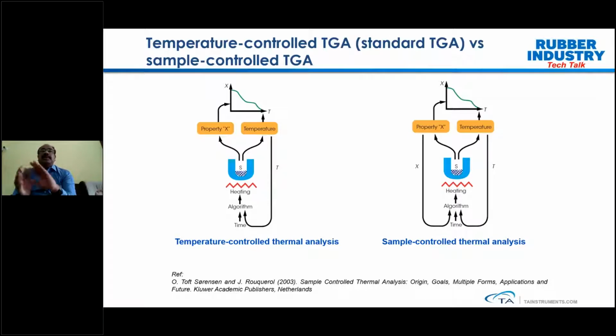One should understand the difference between a temperature control TGA and a sample control TGA. In sample control TGA, we are regulating the heating rate based on the decomposition nature of your sample. On the left-hand side, we define the heating rate, so irrespective of sample decomposition or weight changes, the TGA ramps up the temperature at the predefined heating rate. Whereas in sample control TGA, as you can see on the right-hand side, your sample weight loss is also part of the control algorithm. At the beginning of the run, the sample is heated at a faster heating rate. As soon as the TGA senses a sample weight change, it slows down the heating rate and allows the particular decomposition to complete.